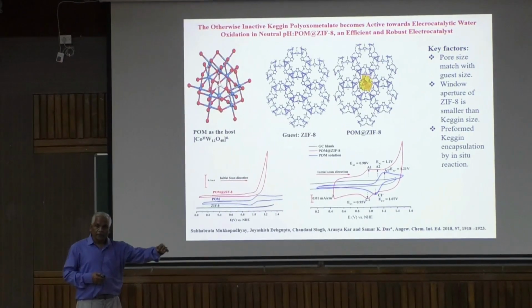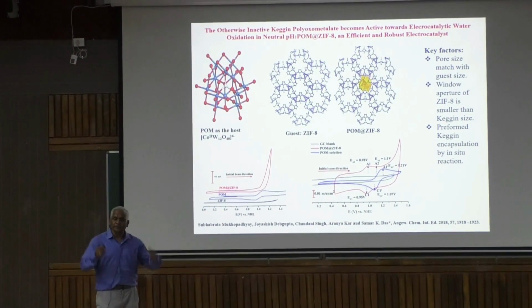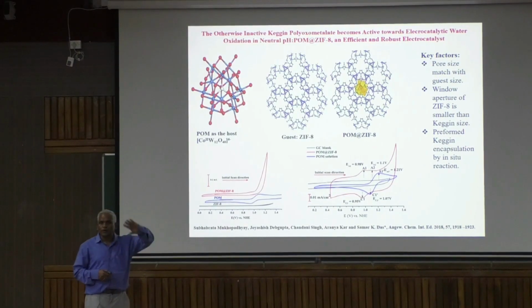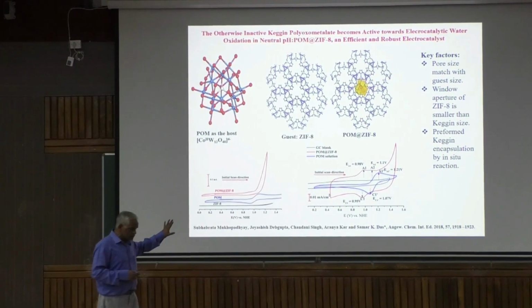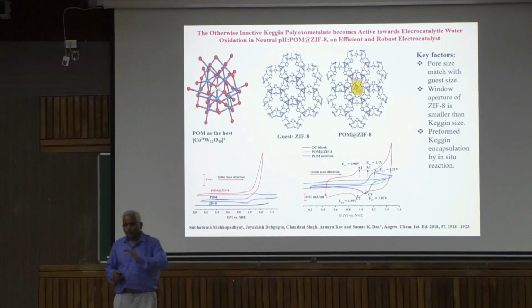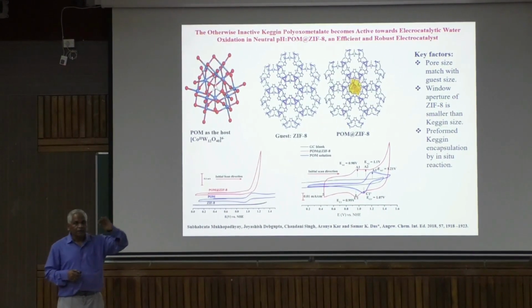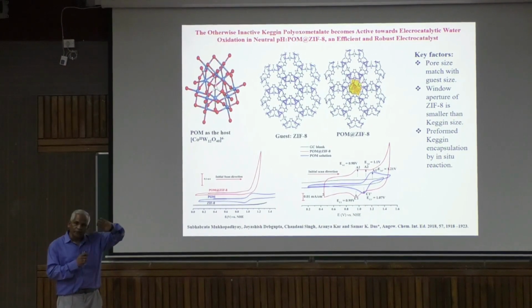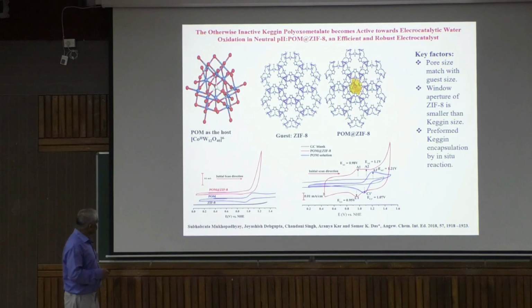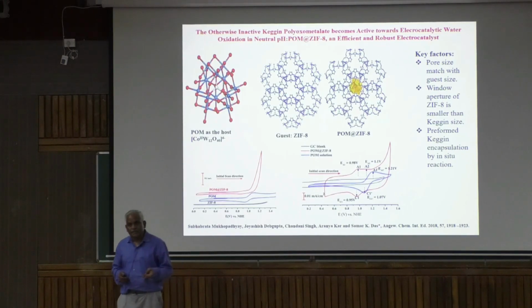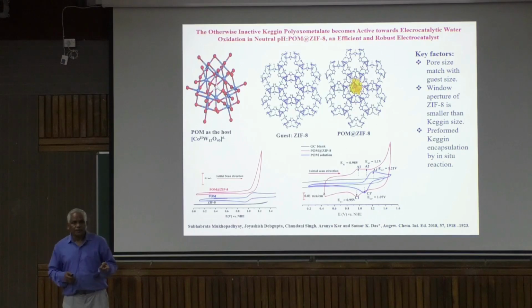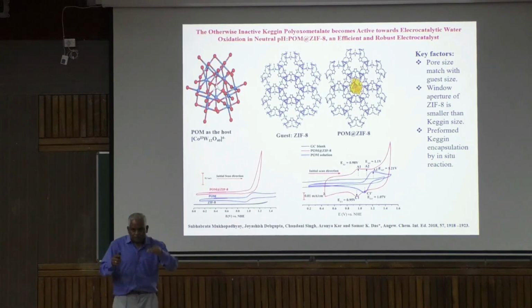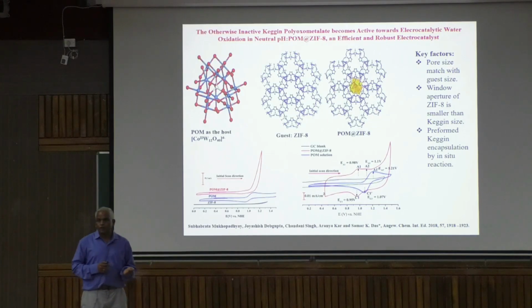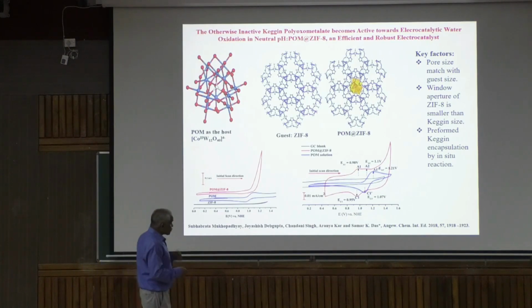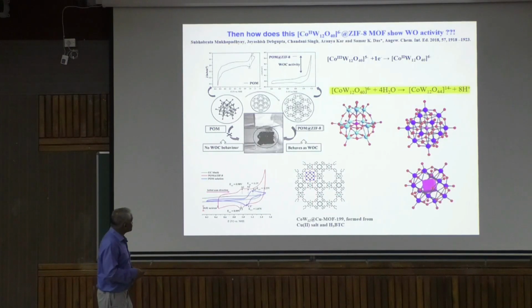Again, you keep the same electrode and use it after 7 days, and you can continue the same thing. This is a heterogeneous system. What we do is coat it on the electrode. Let me tell you how we do the heterogeneous one. The material is water insoluble, so we coat it on the working electrode with some carbon material, and we use Nafion as a binder. It will be coated nicely and will not come out. Then we do the electrochemistry. We find out 3 parameters: faradaic efficiency, turnover frequency, and overpotential. Overpotential should be very low, like within 300 to 400 millivolts. This is a good catalyst. Faradaic efficiency should be 90%, meaning there is no other reaction going on. And of course we check the stability, how stable it is.